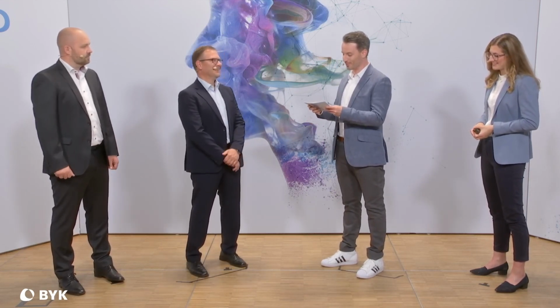The last one's for you two. Okay. Firstly, to Markus. Which pigments were tested in automotive coatings? Oh, yes. I'm not the expert for automotive coatings, but luckily during the preparation of the presentation, I discussed this in a deep dive with my colleagues of the automotive department. They tested especially titanium dioxide, iron oxides, and also bismuth vanadate. So in general, inorganic pigments. I saw the results, and with all these inorganic pigments they always achieved very low viscosities, much lower versus a market standard, and very good long-term stability of these slurries. So in general, for automotive coatings, I would say for all kinds of inorganic pigments, Disperbyk-2018, 2019 are excellent additives. Thank you very much.